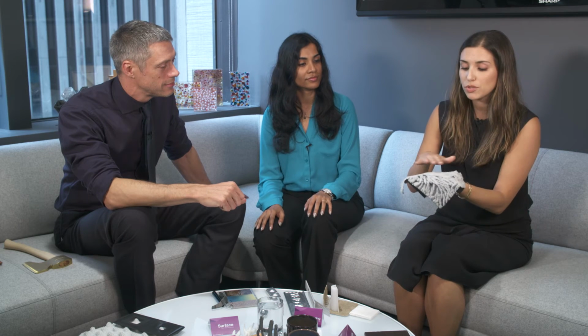So that's achieved by the adhesive being printed onto the surface within this pattern, and the fibers are scattered so that they fall onto that adhesive. Then it's electrostatically charged so that the fibers stand up on end, the same way that your hair would kind of be staticky, right? It's going to stand up on end. Sure. Yep, it's got that same kind of effect. So this is typically used in apparel. It can be used in home furnishings, wall coverings, and you can change the base color, which is the fabric, and then you can also change the fiber color. So you can create different patterns. Here we've kind of got a zebra-like pattern, but it really can be customized depending on what you want.